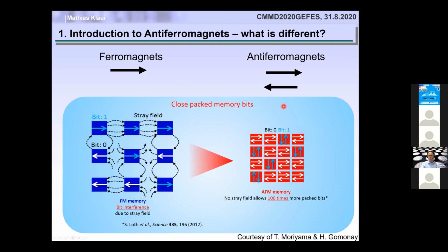And in antiferromagnets, this is very different. You have compensated sublattices, so there's no net stray field. However, also in most antiferromagnets, there's no difference between right and left because the two sublattices cannot be distinguished. So to store information in an antiferromagnet, you have to rotate these two sublattices by 90 degrees rather than the 180 degrees in a ferromagnet. So that's a fundamental difference.